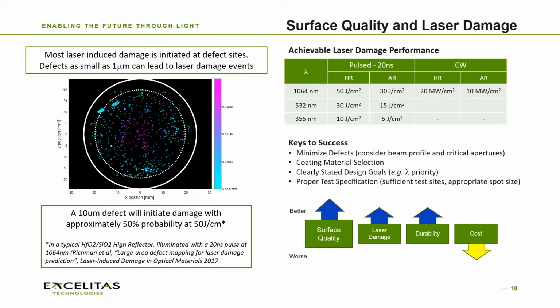But as a reference point, the kind of fluences that well-designed, well-manufactured optics could be expected to withstand at 1064 is around 50 joules per square centimeter for 20 nanoseconds. Now that is highly dependent on the type of coating. It's highly dependent on the spot size and the aperture size that's being tested and being used. But that's kind of a decent rule of thumb.